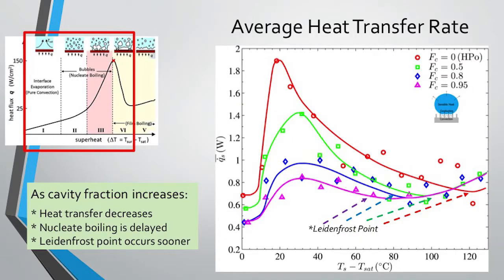This is really actually very important. It kind of looks cool as far as visualizing it, but it's really important because it changes this classical boiling curve that has been known for many years. The red one is the smooth surface, and it fits the boiling curve, and you can see the Leidenfrost point as it starts to level off here before it goes back up again. And then the green is the 50%, and then we're getting more and more cavity relative to surface as we go down to the purple.